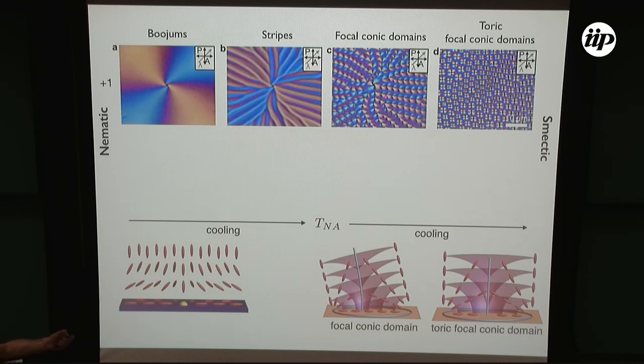In the case of these focal conic domains, you see there's just one blue and one orange in each one, which indicates this tilt, and we're seeing mainly this back region, the side closer to us and the side farther from us, show up as orange and blue. In the stripes, you're seeing oscillations about this original direction into the other diagonals. And I'll have pictures later about what that looks like, but it's oscillations of the in-plane angle about the original direction. No, this is what you get directly out of the quarter wave plate microscopy from the experiment. It's not false color.